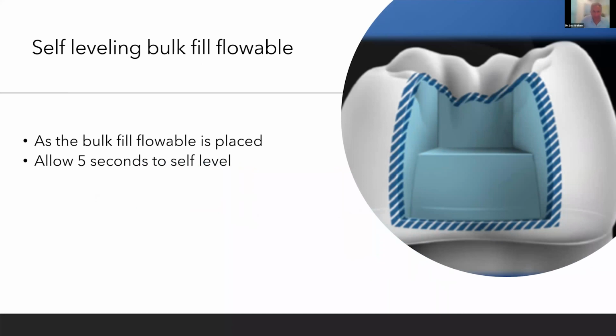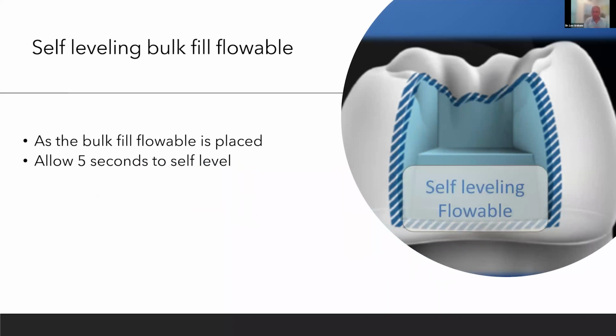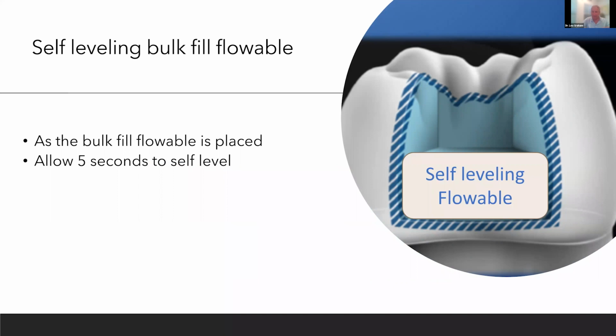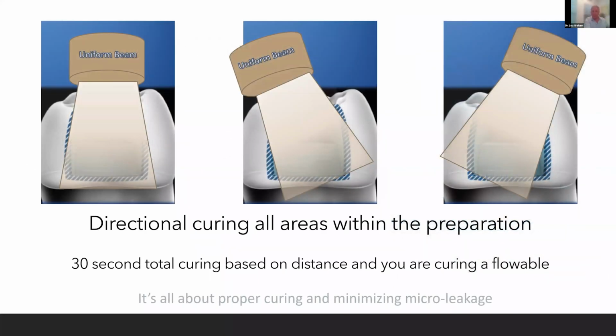So let's talk about this. Here you're placing your flowable. You're going to wait about 5 seconds and let it self-level. Then you're going to take your light straight down and cure for 10 seconds. Then you're going to tilt it from the buccal, tilt it from the lingual, and cure 10 seconds. Why? I have seen so many brown lines along the proximal areas of a box because they weren't cured. You've got to cure them.